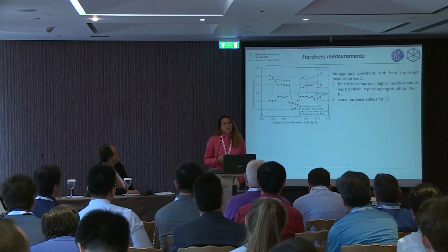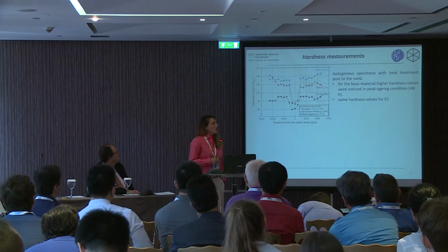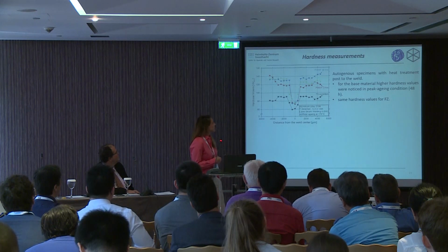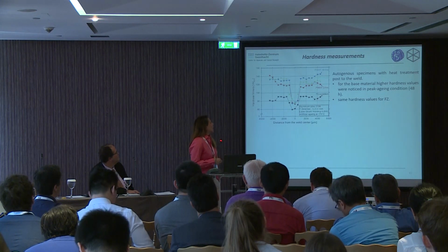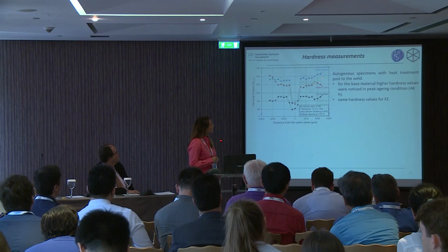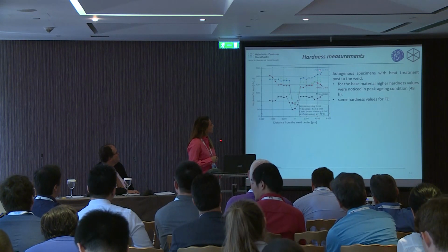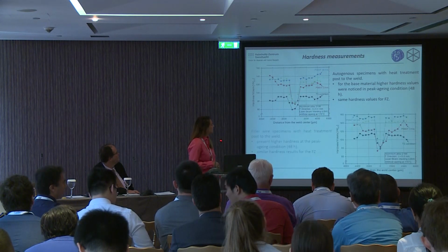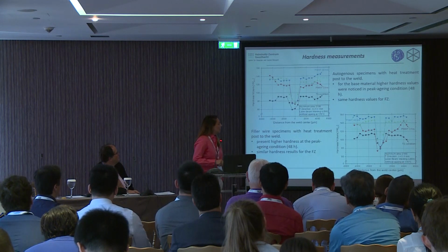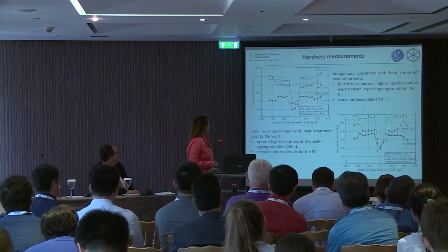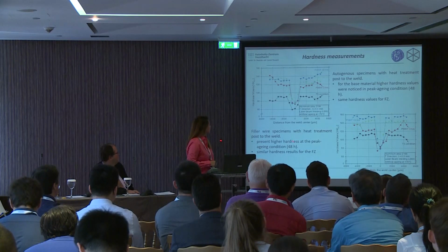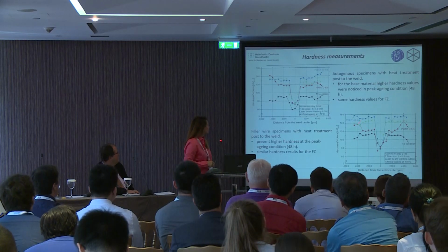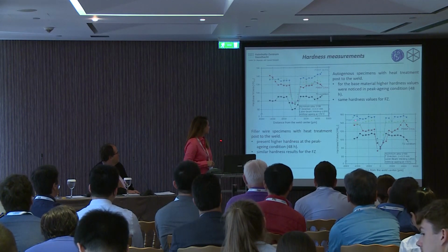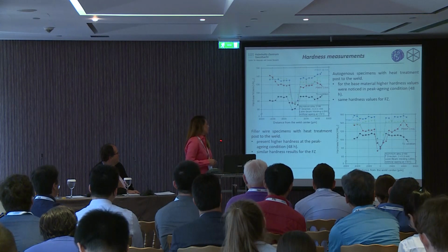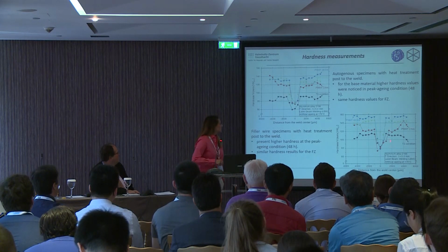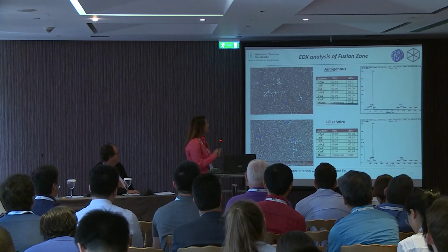For the experimental results and hardness measurements, autogenous specimens with heat treatment post to the weld, for this base material, high hardness values were noticed in the peak aging condition at 48 hours. Filler wire specimens with heat treatment present the same, higher hardness at the peak aging condition at 48 hours. And they have similar hardness results in the fusion zone.